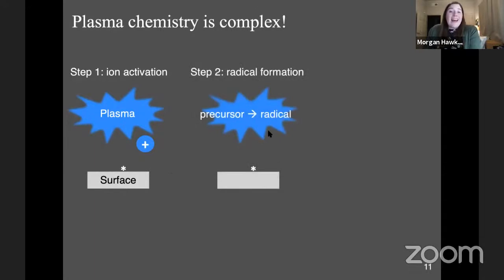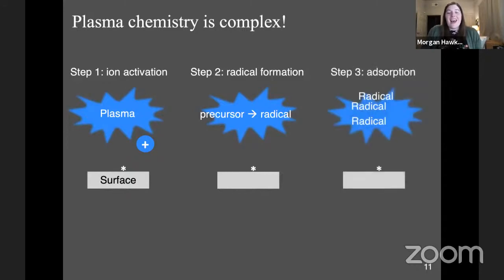So next, the plasma can also generate radicals from the precursor. And this again depends heavily on what the precursor is and the different plasma treatment conditions. But let's say that we have a precursor that generates substantial quantity of radicals. And what can happen is these radicals can interact with the active site, thereby building this film on the surface.